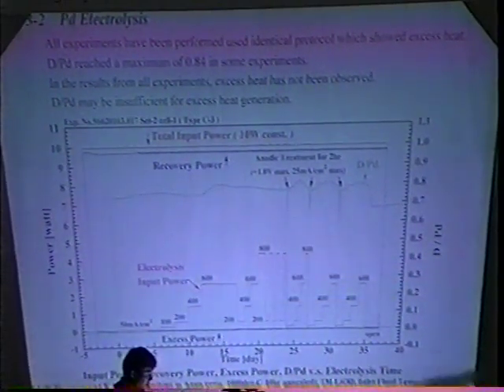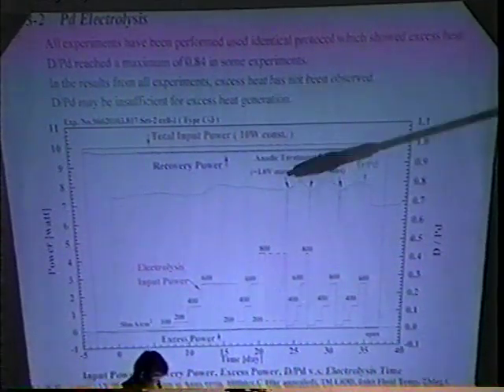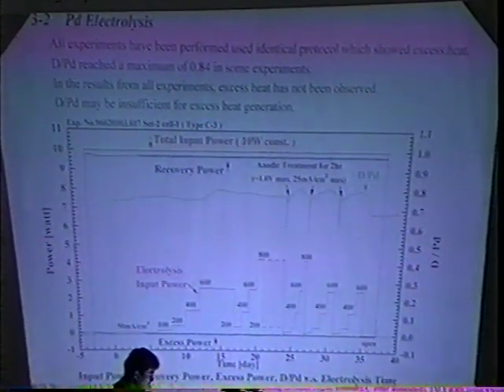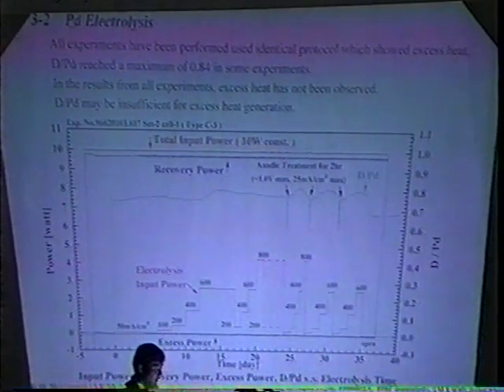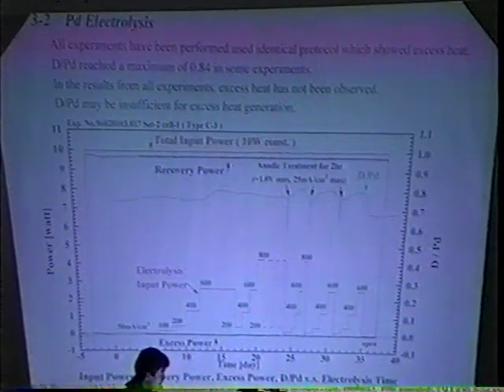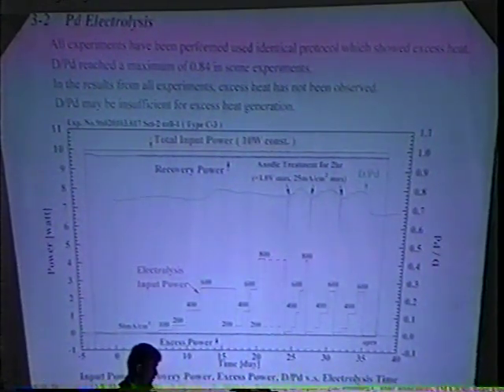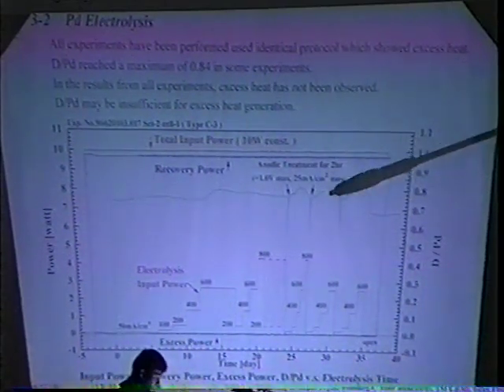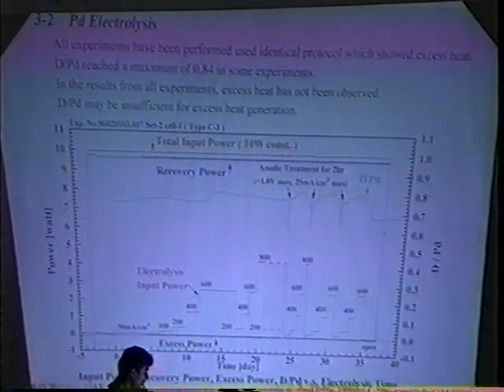These values show the current density. Here, and here, anodic treatment was done. In this experiment, the material and treatment of the palladium cathode and the experimental procedure are identical. They are shown here. D by PD reaches a maximum of 0.84, but decreases at high current density. The calculated result of excess heat was almost 0 watt.